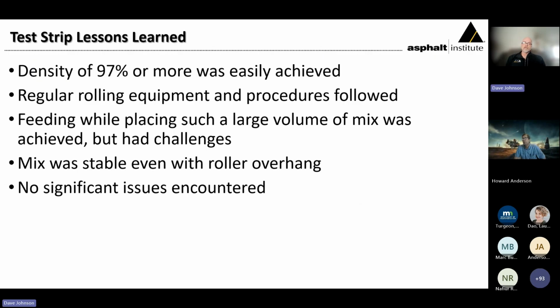What did we learn on the test strip? That achieving densities of over 97% was rather easily done. Regular rolling equipment and procedures were followed. The roller operator for Staker Parsons, she and I chatted quite a bit, and she had anticipated trying to just simply use her normal rolling pattern, and she was willing to make adjustments if that proved to be necessary. But her normal rolling pattern was functioning just fine.